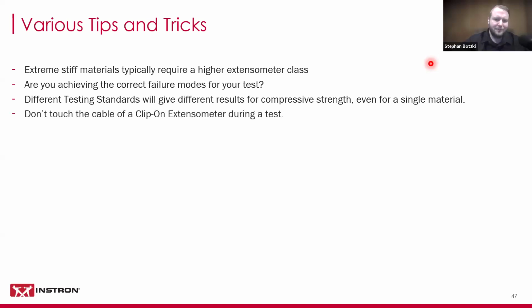Another easy one, and this is really a good one to check out yourself: don't touch the cable of a clip-on extensometer during a test, because it will directly affect your strain measurements. You can best test this with a dummy specimen, or just when the extensometer is connected to your testing machine and you have it laying there, and you look at the strain measurement, and then you move the cable a little bit and just look at the strain reading. It will definitely change.